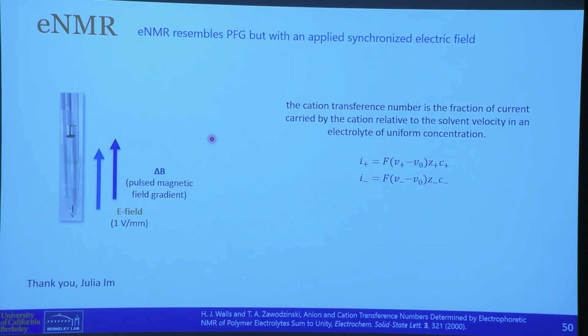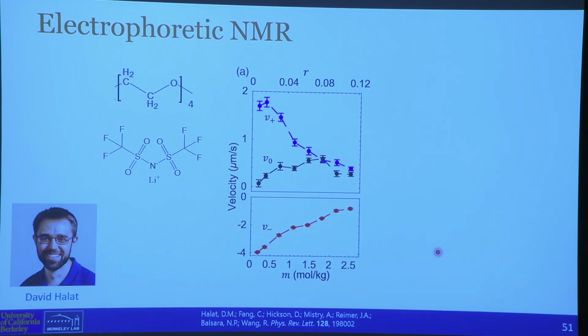If you now take this ratio of currents, you get a transference number that is the cation velocity minus the solvent velocity, divided by the cation velocity minus the anion velocity. The anion moves in the opposite direction, so the denominator is positive. The solvent usually moves with the cation, so that numerator can be negative or positive. In fact, David Halat measured these velocities as a function of salt concentration. You can see as salt concentration increases, the cation velocity goes down, and the solvent velocity goes up. There comes a point at which they're actually equal and close to reversing. And here is the anion velocity. From these measurements, we can get transference numbers with accuracy that we can't get from other approaches.